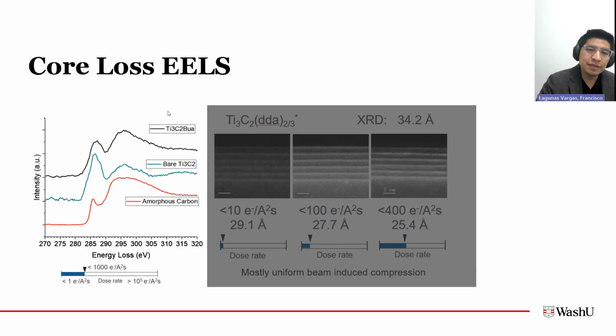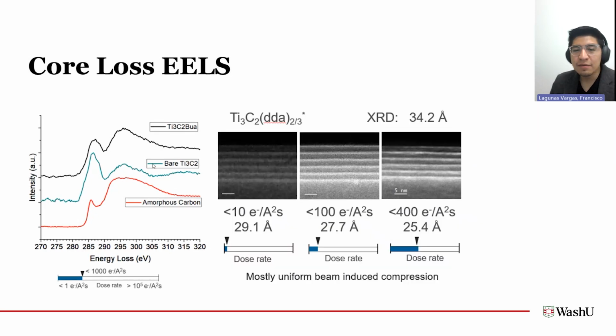However, as you can tell from the comparison of the two, there really isn't any additional carbon bonding that's present here. And what we suspect is happening is that at these dose rates, we are actually amorphizing the carbon surface groups. And instead of having additional fine features, we just overlay this amorphous carbon peak onto it. And using a little more precise, careful dose, correlating dose with our structural information of these MXenes, we began to understand what was happening.